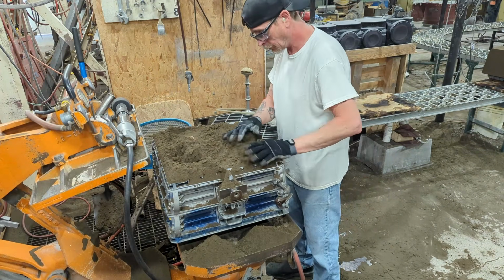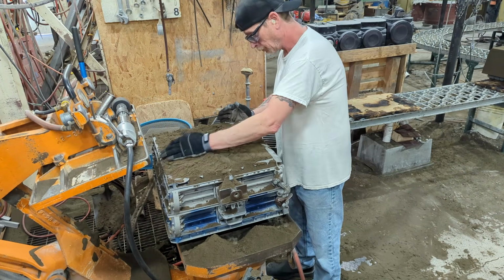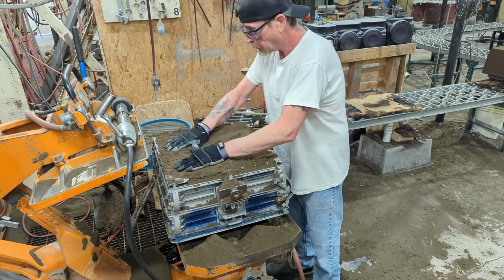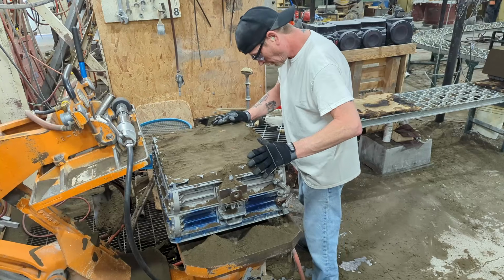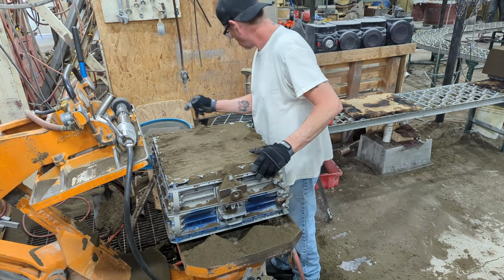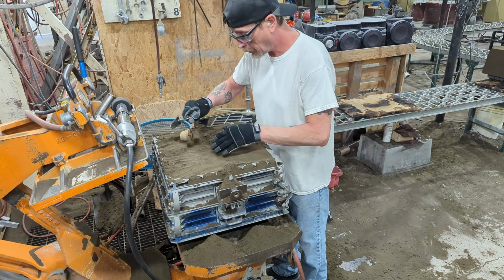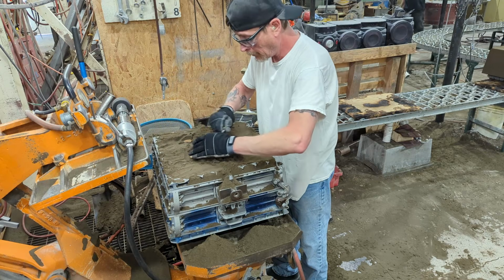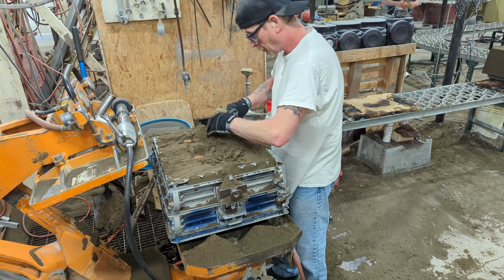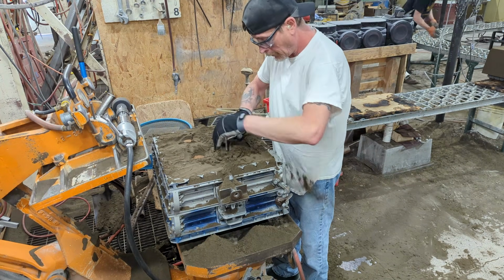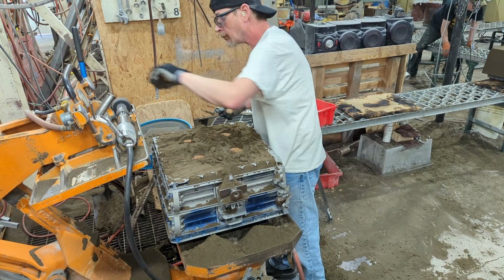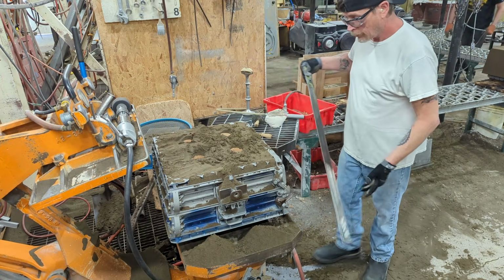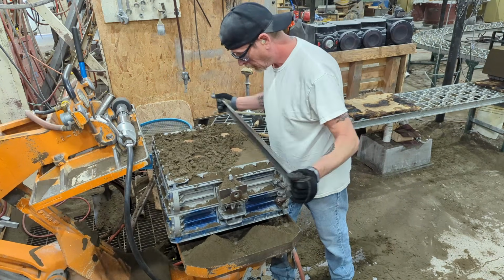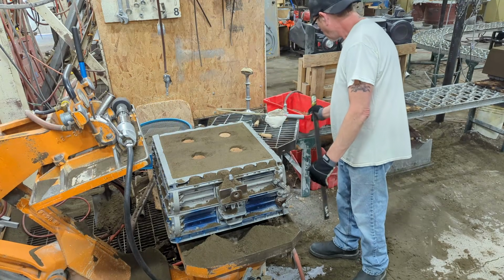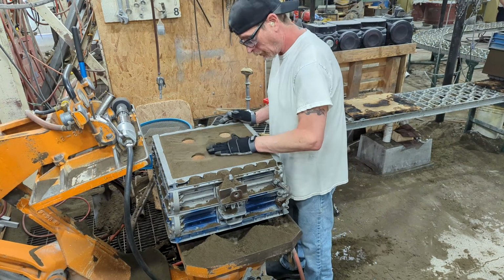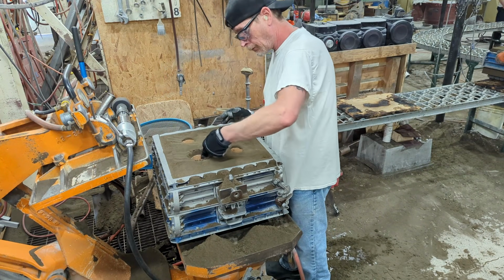After several passes with the rammer, Chad smooths the top of the cope flat, then removes the 4 plugs from the tops of the thermal risers. He scrapes and pats the surface smooth one final time, cleans around each riser opening to remove any loose sand, and blows the entire mold surface clean with compressed air.